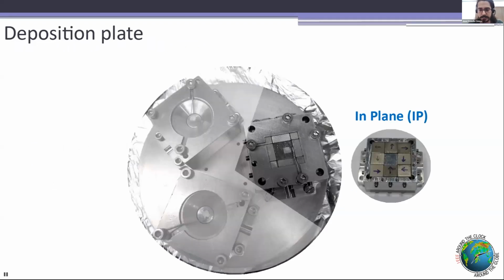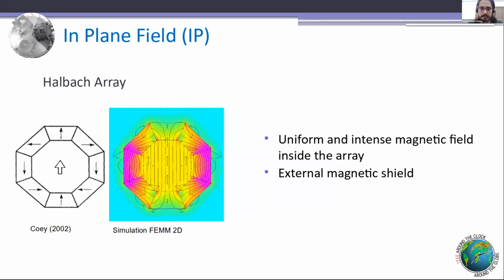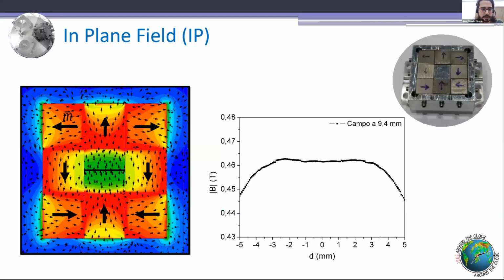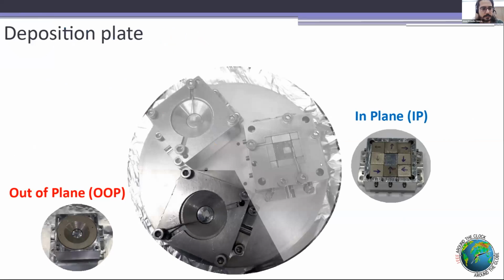One is in plane with the film. We used a Halbach array, which is quite good for our system because it has a uniform and intense magnetic field inside the array, and the external magnetic field is shielded, so it does not influence the others. We performed 3D simulations with synthetic magnets to preview what field we could reach. This is from the in-plane field.